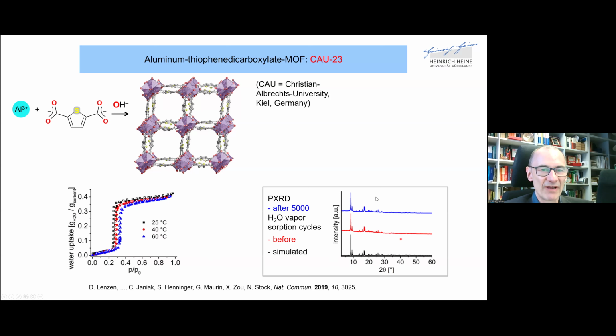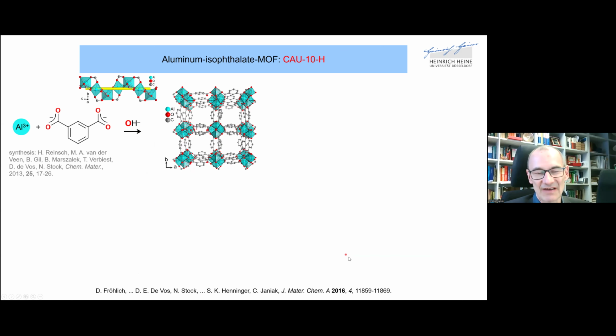cycles, and from powder X-ray diffraction, which is an indicator of the crystallinity or the crystal structure of the MOF, you see there is no visible change in the powder X-ray diffractogram. That means the MOF is still stable after 5,000 cycles. The red diffractogram is the one before, and the black one is the simulated one from the single crystal structure determination.